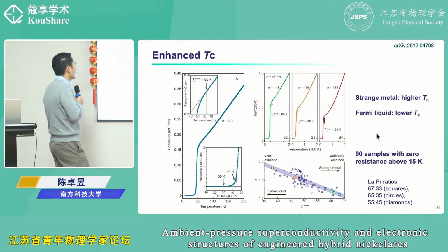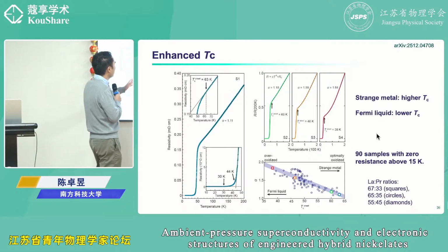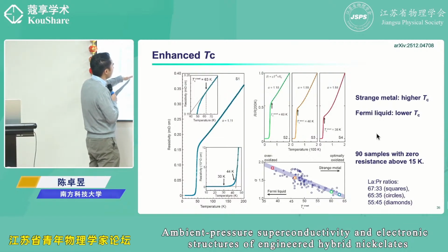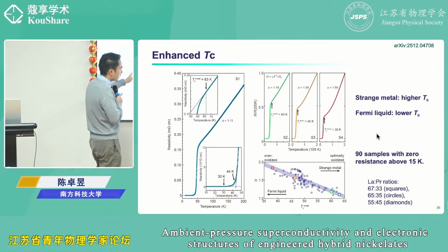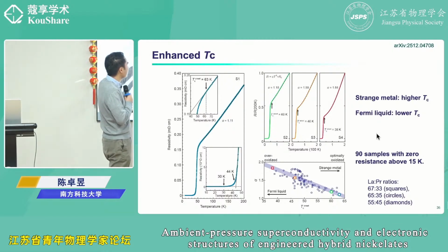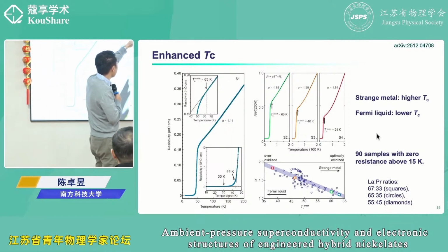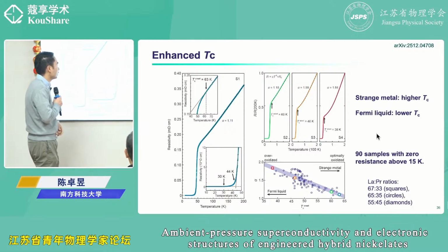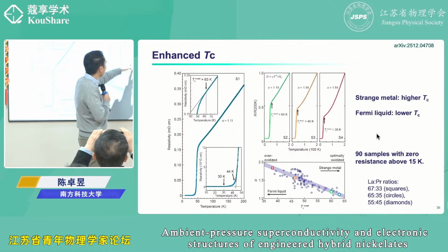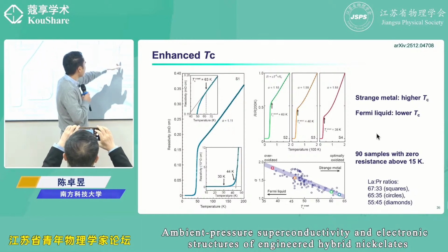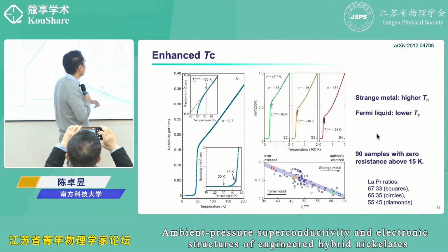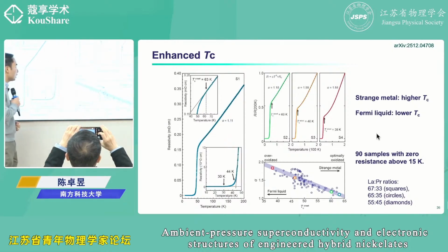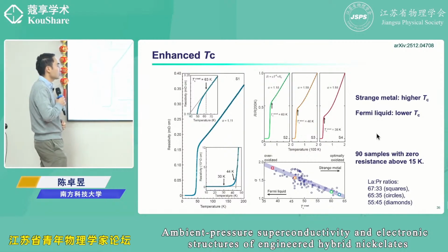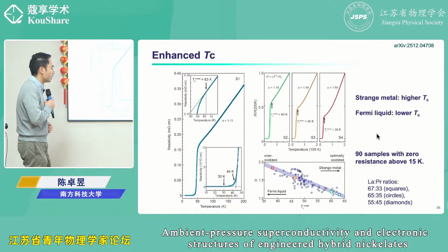Another very important feature is the normal state RT curve. For those 60 Kelvin samples, it's more linear. This is 63, this is 60. These 2 samples, you can see that they are quite linear in the normal state. In comparison, these are lower TC, like 44 and 38. You see the normal state looks more like a T square, this Fermi liquid behavior.